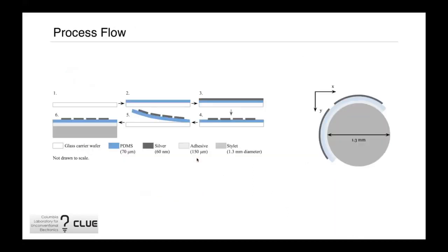To fabricate the device, first a glass carrier is cleaned, treated with UV ozone plasma, and exposed to a fluorosilane in a desiccator as an anti-adhesion monolayer. Then 70 microns of PDMS is spin coated onto the glass and cured. 60 nanometers of silver is then thermally evaporated, and positive photolithography is used to pattern the silver.